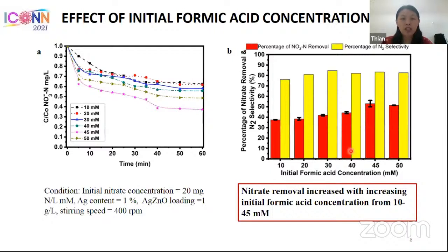And next, what is the effect of initial formic acid concentration? So we can see here from 10 to 45 millimolar of formic acid concentration, it leads to a gradual increase in the percentage of nitrate removal, but beyond 45 millimolar, it doesn't give us any significant improvement in terms of percentage of nitrate removal. So again, similarly, if we keep on increasing the formic acid concentration, there will be a competition between the nitrate molecule and the formic acid for the surface of the photocatalyst. And so if we keep on increasing the concentration of formic acid, it's not going to give us any more